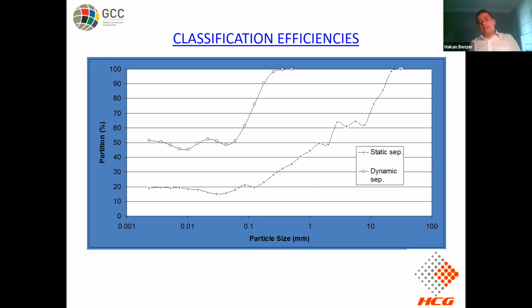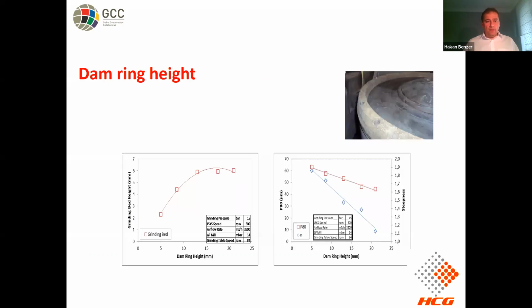And compared to a typical ball mill application, in order to achieve the same strength value with the vertical roller mill, the cement producers have to grind finer. So some of the energy advantage is consumed because of the quality loss of this steep size distribution. But this can be an advantage for the mining industry. Of course, working deeply with these equipment and also working with the pilot equipment, we had the chance of evaluating the operational parameters on the performance.